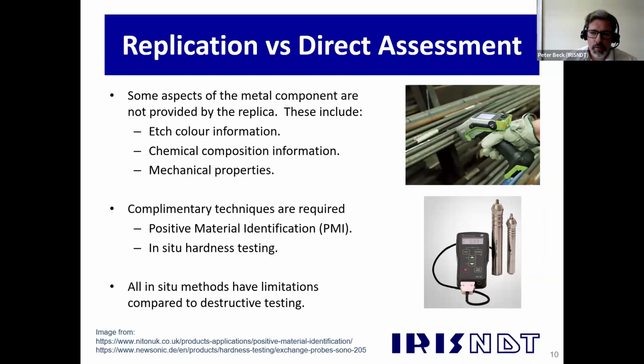So there are some limitations to replication. Firstly, there are some features of the metal that aren't transferred into the replica. So these are typically things like the color of the etch. So sometimes if you're looking for sigma phase, for example, ideally you would use a colored etch so that it etches the sigma a kind of browny color. One thing is that with this, it's not got any color. It's always going to be black and white, basically. So that is a limitation. So you'd have to make some allowances. So sometimes it might be that you'd have to say it's consistent with, but it's not definite.